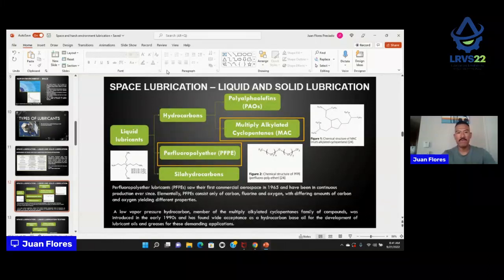So these are some examples of the different space lubricants that we use. We can use liquid lubrication, which are normally hydrocarbons and PFPEs. And there is a new generation of liquid lubricants that have very low vapor pressure, which are called the silahydrocarbons. In terms of the hydrocarbon, PAOs are really not the best because they don't have really good vacuum stability. But there is a new generation.